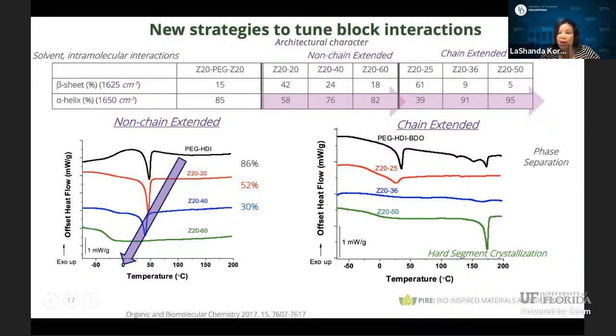For the Z25, you now can start to see that you have phase mixing that occurs within the soft domain, and then you are having a hard segment crystallization peak much higher than that even of the control system. Again, this aligns well with what we see in the ATR-FTIR, where you have phase mixing with the lysine and the PEG, and then you're able to have a pure hard domain.